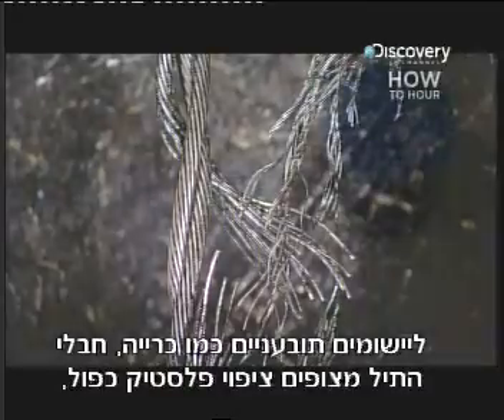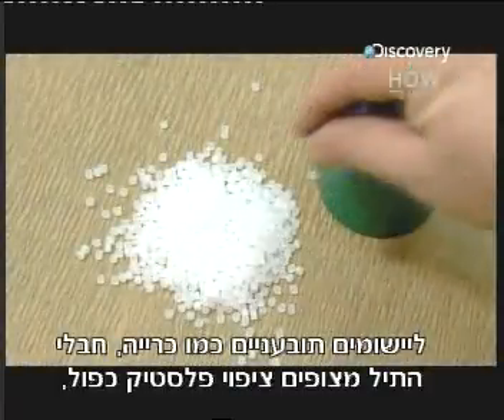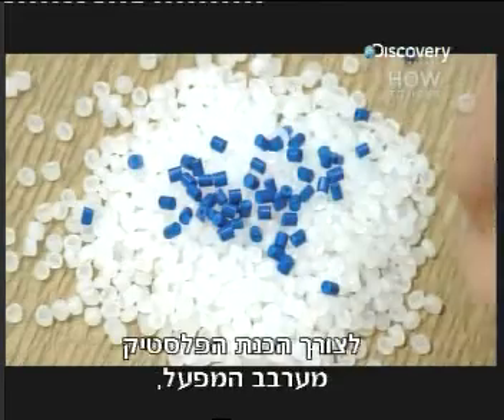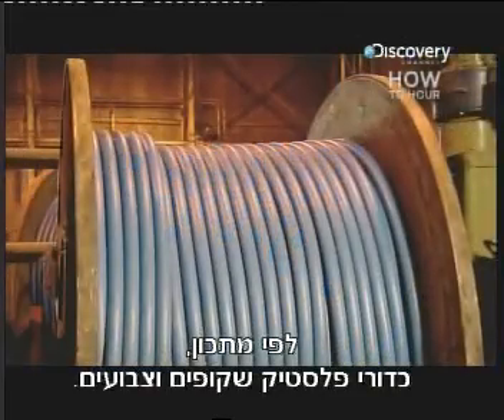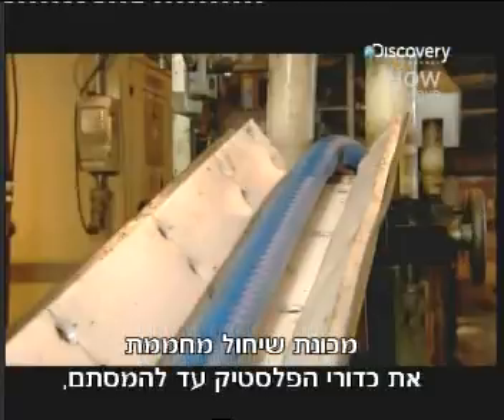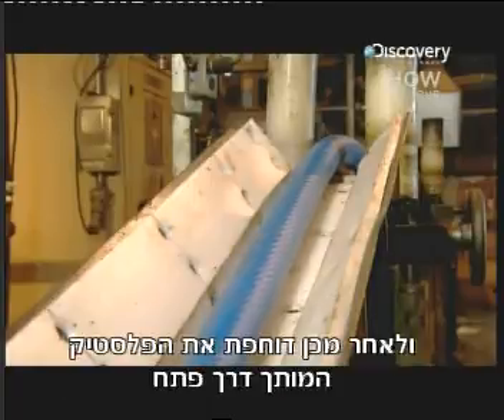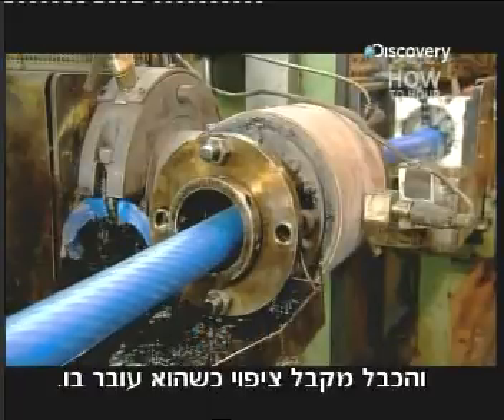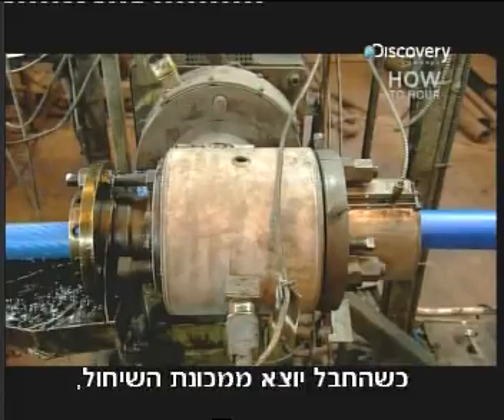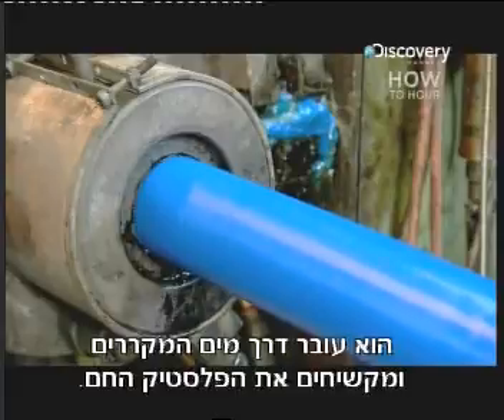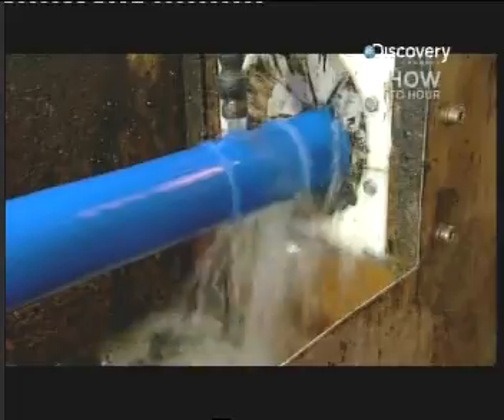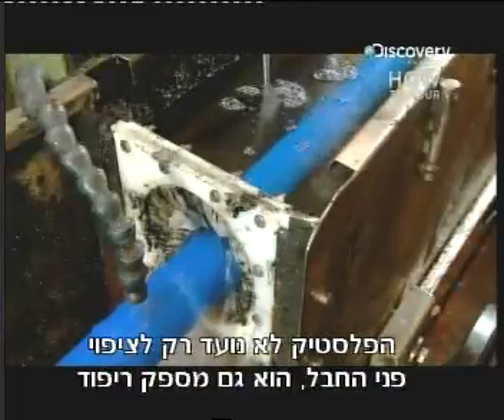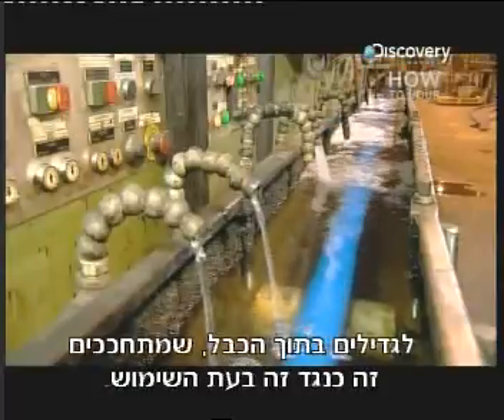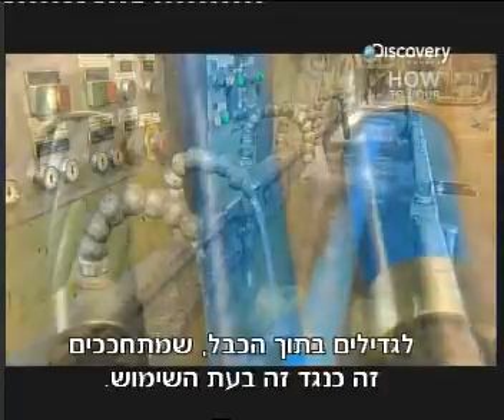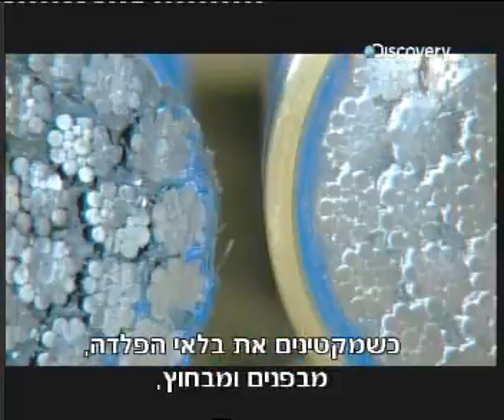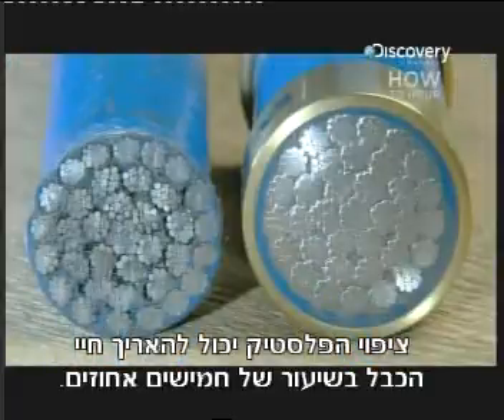For certain demanding applications such as mining, wire ropes are double-coated in plastic to protect against wear and tear. To prepare the plastic, the factory mixes a recipe of clear and coloured plastic pellets. An extrusion machine heats the pellets until they liquefy, then forces the molten plastic through a die, coating the rope as it passes through. As the rope exits the extrusion machine, it passes through water, which cools and hardens the hot plastic. The plastic not only forms a jacket on the rope's surface, it also provides cushioning when the strands inside rub against each other in use. By reducing wear and tear on the steel both internally and externally, plastic coating can extend the life of a rope by up to 50%.